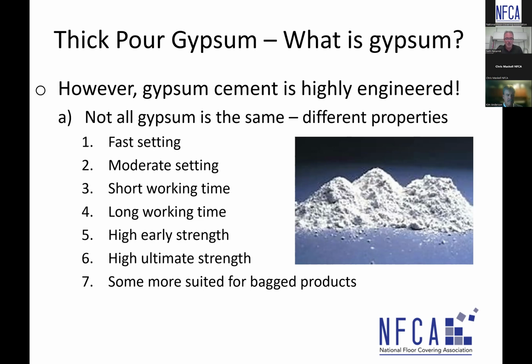Yeah, it certainly is. And that's one of my talking points here today, one of the biggest causes of issues. It'll be in a future slide: the GC closing up the building, closing up the area, and all the moisture gets into the air, and you're basically creating a greenhouse effect. We have to have proper drying happening, and gypsum takes some time to dry. It's typically a week for floor covering, at least from a drying standpoint, and your conditions could mean longer than that. That particular case was 50,000 feet, and it was literally just crumbling, chunks of it coming up. Horrible situation. Yep, not good.